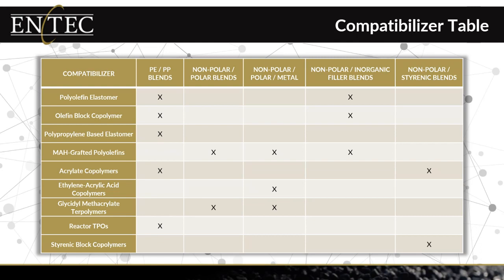But I would argue that based on my experience, olefin block copolymers tend to perform the best. And the reason is, again, as a block copolymer, they work really, really well to stabilize that interface and to reduce the interfacial tension. And they work very well in polyethylene, polypropylene blends. Now, that doesn't mean those other modifiers won't work. It just means that in my experience using some of those various products, in most of the applications with PE contamination in PP, you're going to see that the block copolymer just performs better.